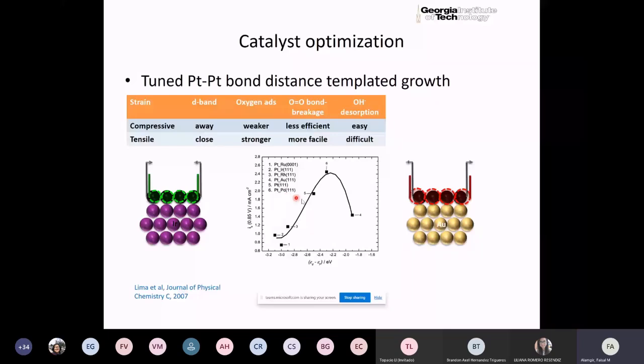it gives a little bit better performance if you have, so if you look at palladium as the substrate, the palladium seems to want to squeeze the platinum atoms a little bit tighter because palladium is a little bit smaller. So I misspoke a little earlier. I said tensile, it should have been compression. So when you have palladium as the substrate, it applies a compressive strain on the platinum, and that compressive strain seems to help. So that's something to keep in our minds.